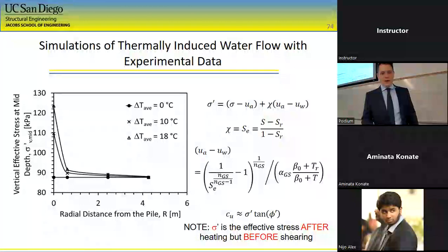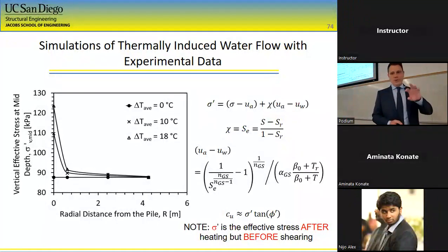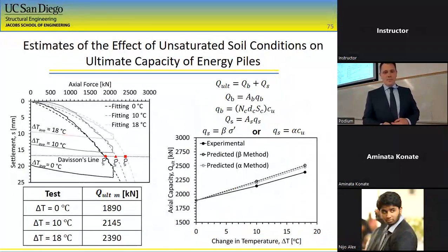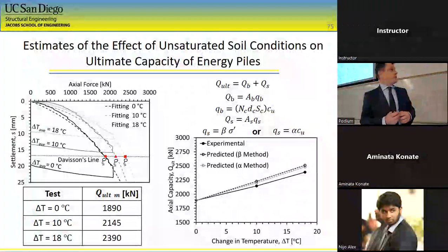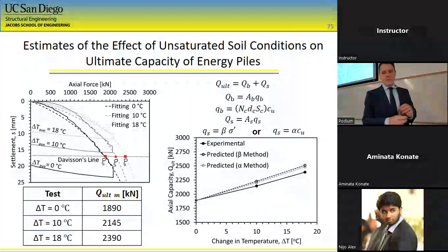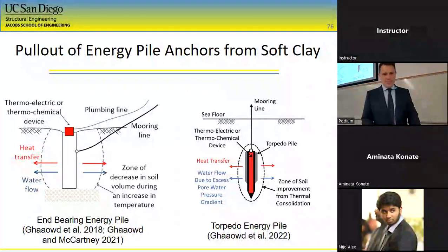And with that, we can do an effective stress analysis. We know what the change in water content is. We can predict what the suction is and get the effective stress. So with this, we know how the effective stress is changing with the drying of the soil due to increases in temperature. And we can then put that into effective stress analysis here to see how the side shear capacity is changing due to the drying of the soil. And our predictions with either alpha or beta methods were almost spot on with the experiments. So just the final example here.